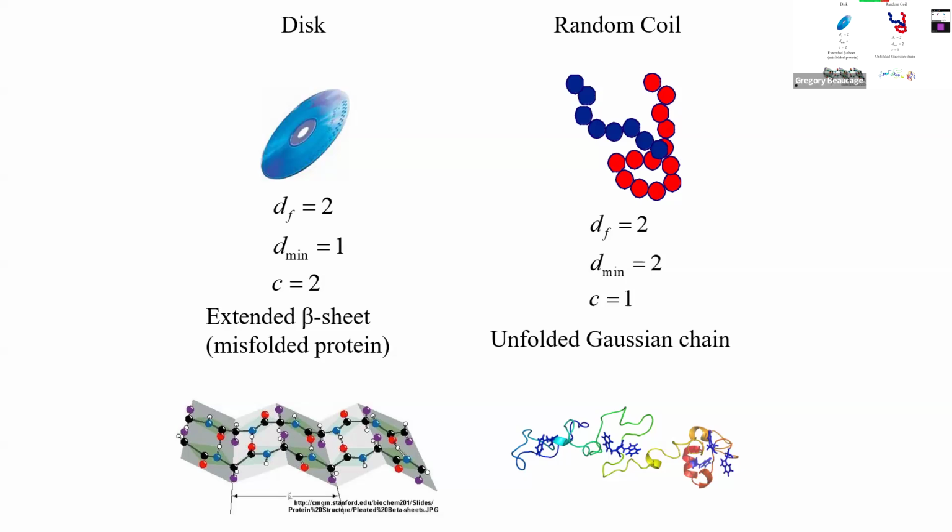So if it's totally random, which is Gaussian, there's no enthalpy, so there's no effect of temperature on it. That means if you have non-bonded fibers, then the processing conditions aren't going to affect much the density of the fleece that you make. But if you have bonded fibers, then the bonding conditions are going to have a big effect on the fiber size in it, so you'll make a denser fleece.